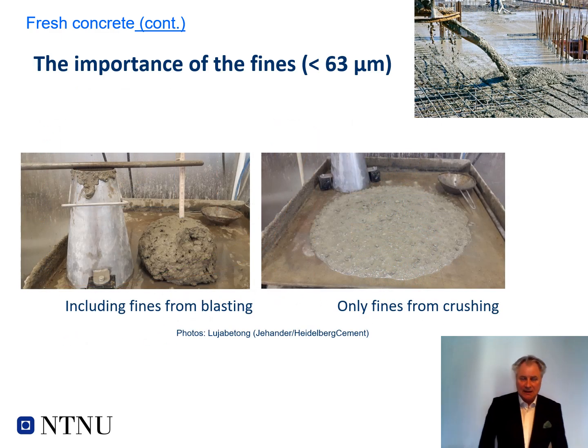Another example from Sweden, where in a quarry, first they included the fines that were created by the blasting. So this is also a crushed sand used. When they included the fines from the blasting, they got a very stiff concrete. If they had exactly the same mix recipe, but they removed the fines from the blasting and only had the fines from the crushing, you can see they have a completely different, flowable concrete. So this is very important to remember, that the finest of the filler in an aggregate will have very much effect on the flowability and the rheological properties of fresh concrete.